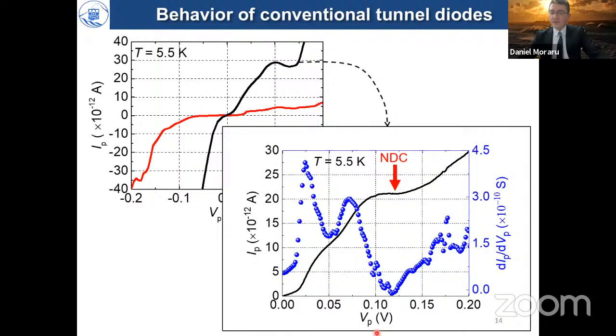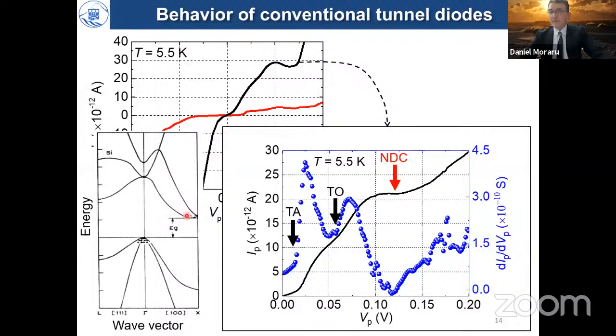And when we take a first derivative of these characteristics, we can emphasize very clearly where these contributions start, and that coincides very well with the energies well known for transverse acoustic phonon. This is about 18 milli-electron volts in energy, and respectively transverse optical phonon, which is very near to 60 milli-electron volts. So indeed, as expected for the indirect bandgap silicon, we observe TA and TO contributions to the current in this type of device. So I mentioned before that because we have electrons in the conduction band at a different wave vector and holes in the valence band at the gamma point, when the band-to-band tunneling has to be achieved, we have to compensate the momentum difference at least by absorption or emission of phonons. And this is what we're seeing here.